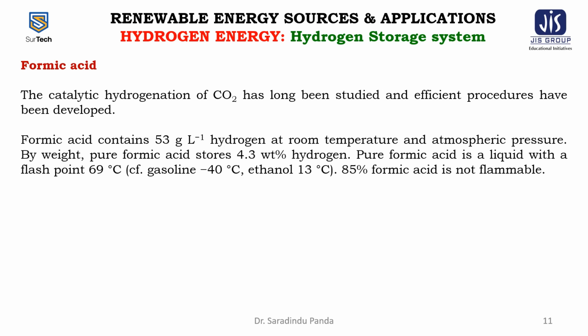Formic acid contains 53 grams per liter of hydrogen at room temperature and atmospheric pressure. By weight, pure formic acid stores 4.3 weight percentage hydrogen. Pure formic acid is a liquid with a flash point of 69 degrees centigrade. With reference to this, gasoline is minus 40 degrees centigrade and ethanol is 13 degrees centigrade. The 85% formic acid is not flammable.